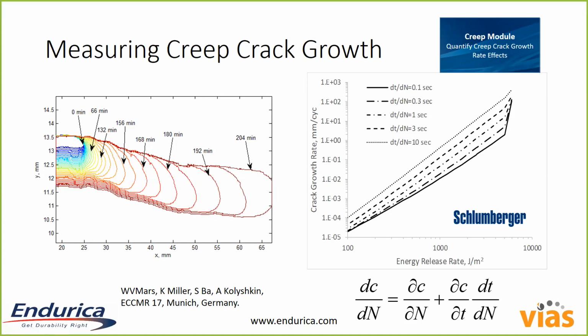And the Endurica software, the FE-Safe Rubber software, if you give it the creep crack growth rate curve and the traditional fatigue crack growth rate curve, it will use this rule that I'm showing in the bottom right to come up with a combined creep fatigue crack growth rate. It's the cycle dependent crack growth rate plus the time dependent crack growth rate, accounting for the period of each cycle, right? So the model knows how to deal with this time dependence.